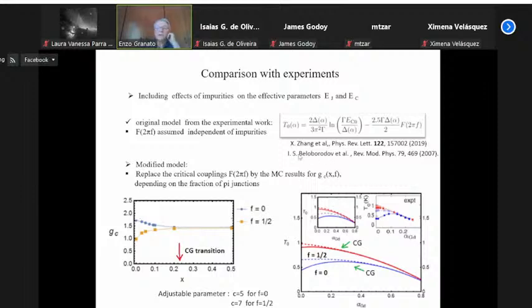In order to compare with the experiment, we have to take into account the fact that the Josephson coupling and the charging energy also depend on the impurity concentration. So we can go back to the model used in the experimental work, where the activation energy has two terms, but with some modification. In this model, the first term was the charging energy normalized by the impurity concentration, the Josephson coupling, and the function F was assumed to be a constant. But F actually is the critical coupling for the transition, and as we just saw, this critical coupling depends itself on the impurity doping, being different for zero field and for 1/2.